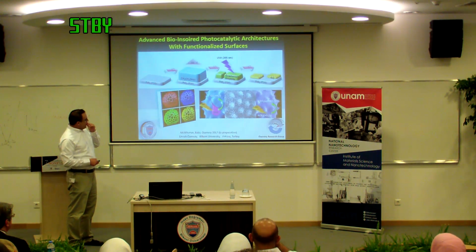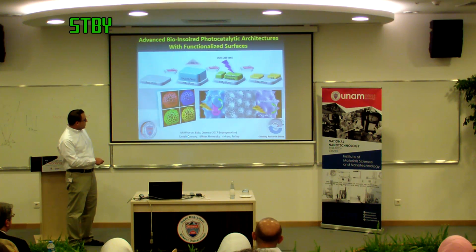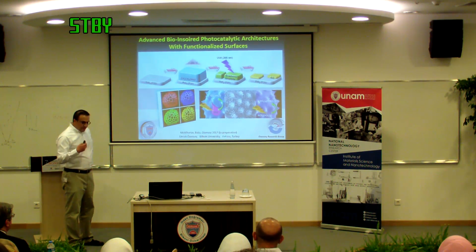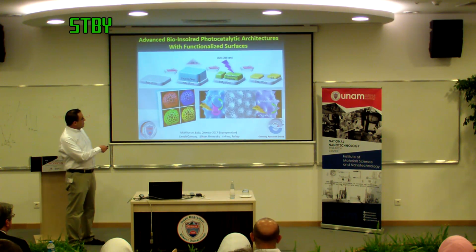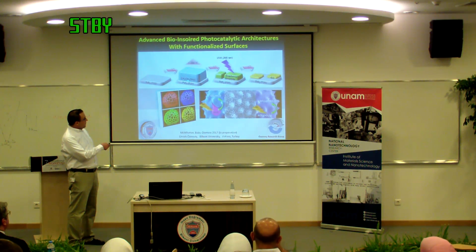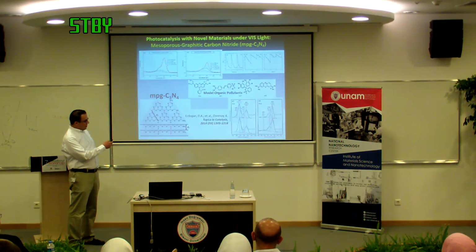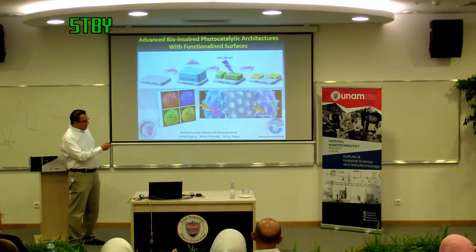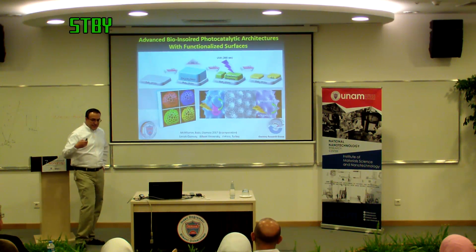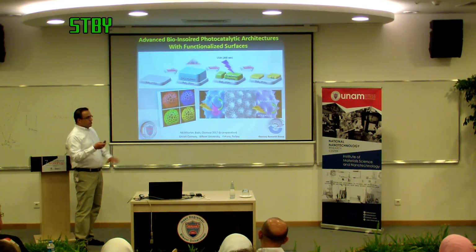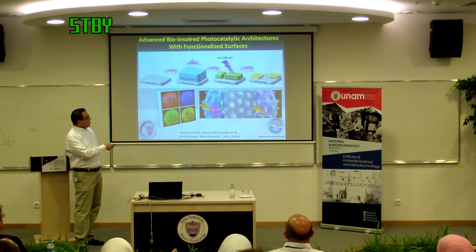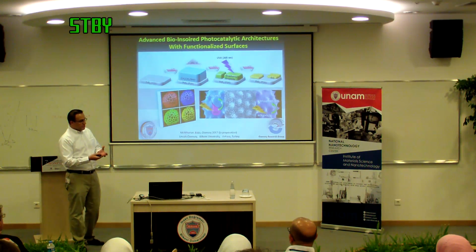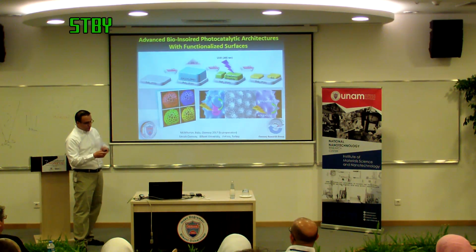What we're doing right now, this is Sean McWhorter's, one of my students' thesis, that you can further improve the surface activity by functionalizing these surfaces using thermal and photocatalytic means. For instance, you can generate some special surface functionalities on titanium and/or graphitic carbon nitride. For instance, you can put some oxygenates, alcohols, aldehydes, acids. Glycerol works very nicely. Then you can treat them with illumination, UV light. You break some of the bonds, you generate new chemical functionality, you heat them, calcine them, and make the proper surface functionality.